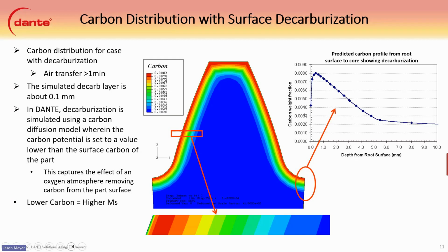In DANTE, the way we simulate decarburization is using a diffusion model where the carbon potential is set to a value lower than the surface carbon, and so it lets the surface gas out the carbon there. And this captures the effect of oxygen removing the carbon from the part surface. And the big thing here is the lower carbon equals a higher MS, martensite start temperature. So when the part is actually quenched, the outside transforms first, and then the subsurface transforms. And that's the problem we talked about earlier, where when the inside transforms, it pulls the surface into tension. And since it's as-quenched martensite, it can crack easily under high tension.